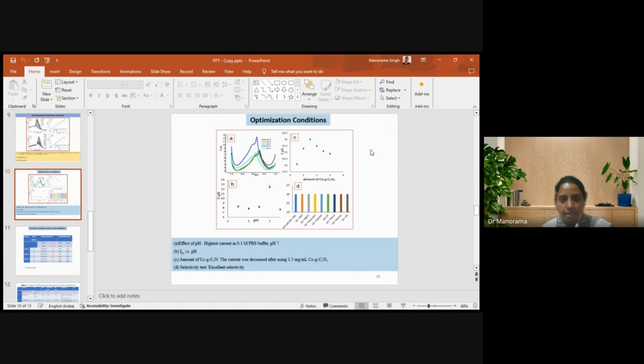So for this study, we have optimized the conditions also. We have first studied the effect of pH, which pH we have to use for this kind of study. So we have recorded the response of the quinol in 0.1 molar phosphate buffer solution in pH 4, 5, 6, 7, and 8. And we have found the maximum current in pH 7. That's why we have done all the electrochemical study for the quinol in the pH 7.